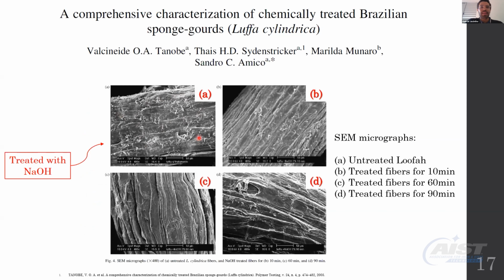In picture A, the untreated loofah has a thick layer of lignin on its surface, blocking the pores and cellulose fibers. With the addition of sodium hydroxide, the lignin is removed. In figures B, C, and D, the concentration of sodium hydroxide is the same, but the treatment times are different. We can see in figure B that there is a good removal of lignin from the surface, exposing the pores of the cellulose fiber. In figure C, there is more exposure of the pores, but in figure D, with 90 minutes of exposure, the fiber starts to get destroyed, and this is not good for the adsorption of the metals in the wastewater.